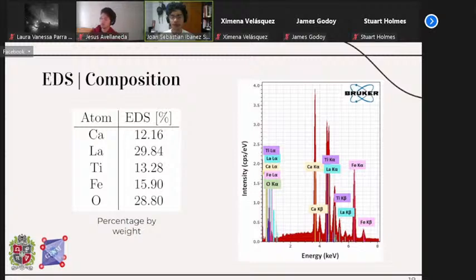In particular, they differ from the theoretical by only, let's say, 3% at most. The lanthanum was the one that had the biggest difference, and we believe that this difference was due to the problem that EDS has with measuring the presence of atoms with atomic number smaller than 10. In this case, given that we are working with oxygen, which has an atomic number of 8, it is possible that it was overestimated or underestimated, and that difference was shown in the lanthanum as well.